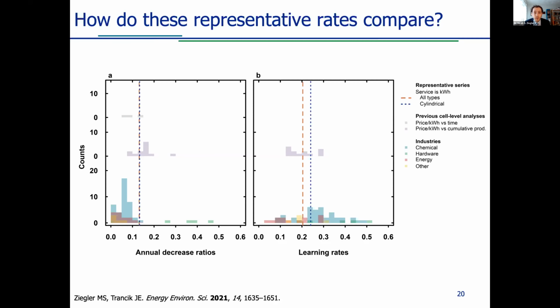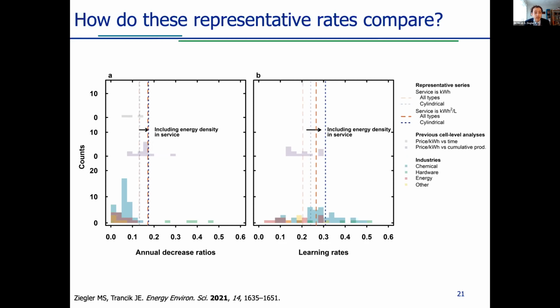And we can see, even with this constrained definition of service, lithium-ion batteries have improved more rapidly than many other technologies versus time, but they're towards the middle top of energy technologies and the middle bottom of chemical technologies. If, however, we expand our definition of service to include energy density, we find that lithium-ion batteries have improved much more rapidly than many other technologies versus time, and now their learning rates are towards the top end of energy technologies and the middle top of chemical technologies. So overall, we've been able to greatly reduce the data uncertainty and reliably measure rates of improvement. And we find that the improvement of lithium-ion technologies, its rate is comparable to that of solar photovoltaics, which is often held up as a prime example of a rapidly improving clean energy technology.